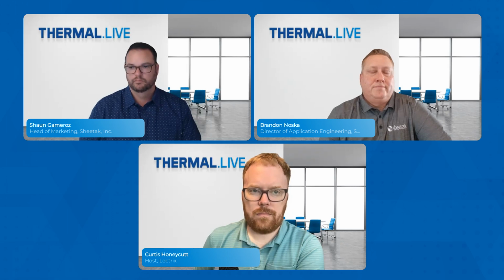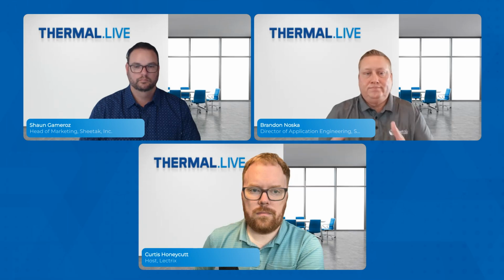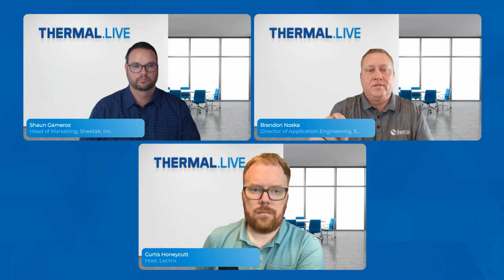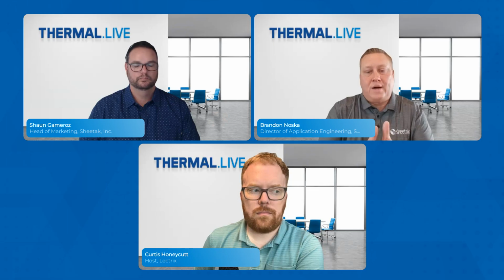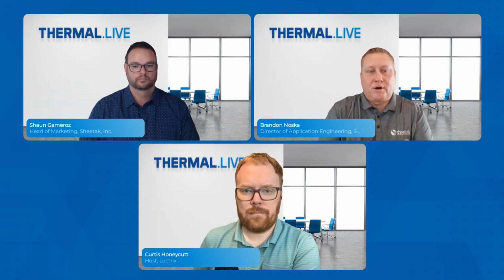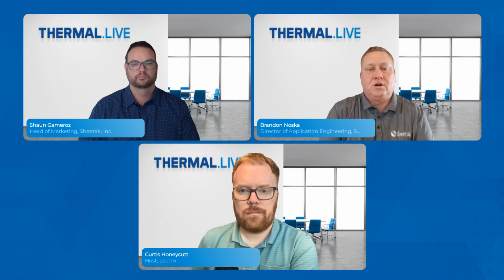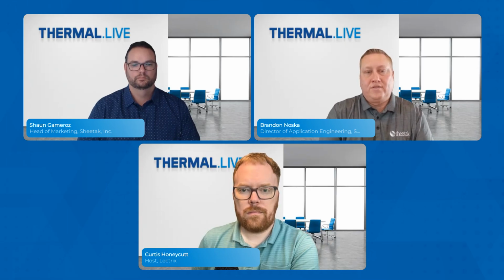Typically, we use the extruded material, so hot pressed or extruded materials, because those give better material properties, better Z properties that I mentioned before, and also better mechanical strength. So in order to get to the geometries that I mentioned for the optical transceiver cooling, the leg geometries being maybe 0.3 by 0.3 millimeters and very thin, say 0.5 or 0.6 or maybe 0.3 millimeter, in order to hold the geometry and not have chip-outs and cracking, you need it to be very mechanically strong. And the only materials that will allow for that are the extruded or the hot pressed material. The crystalline just won't allow you to get there.